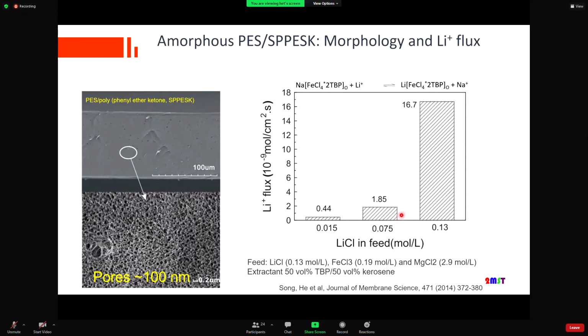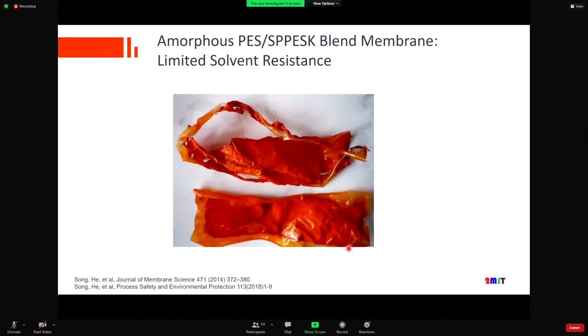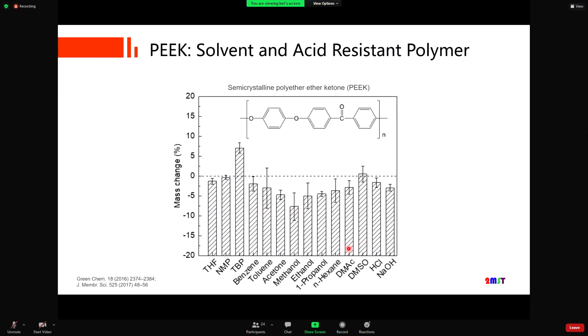It works fine. You see here the flux as a function of the lithium chloride in the feed. But unfortunately, this polymer membrane is not stable in a large variety of organic solvents. So our selection starts from another polymer.